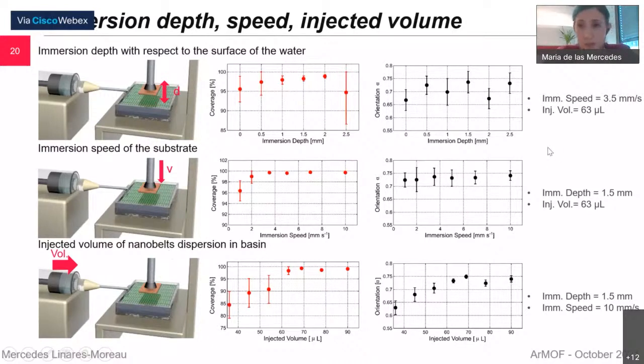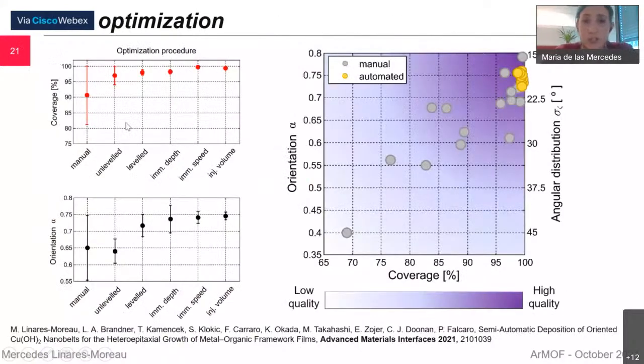And then, with a fixed immersion depth and fixed immersion speed, we studied different volumes that we could inject into the water basin, and we found also a clear trend where the coverage and the orientation are both improving until this point. So we chose 63 microliters of the solution as the chosen volume. This optimization process allowed us to improve both the coverage and the degree of orientation of the substrates.